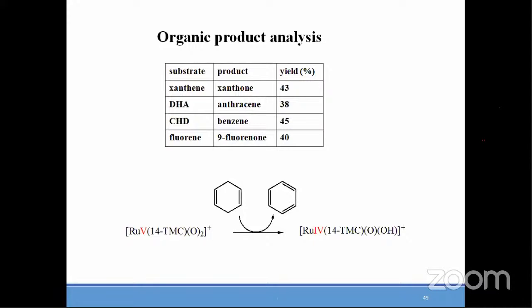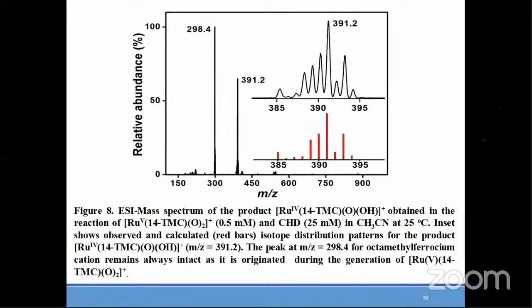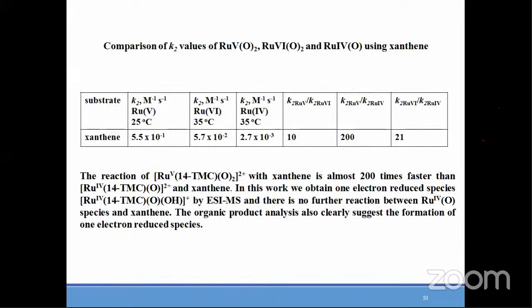So this was the proposed pathway for this reaction. This work is not published, but we propose that a ruthenium(IV) oxo species is forming in these reactions with axial ligand OH, and therefore there is no further reactivity. OH is more nucleophilic, and for this we also have evidence with the mass, so there is no problem. Mass and EPR are there.